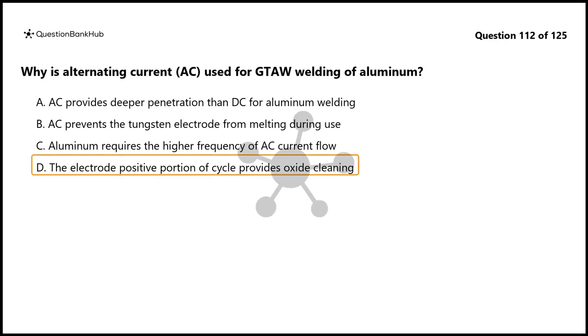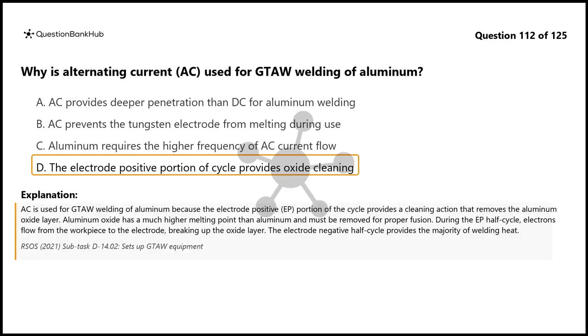The correct answer is D. The electrode positive portion of cycle provides oxide cleaning. AC is used for GTAW welding of aluminum because the electrode positive, EP, portion of the cycle provides a cleaning action that removes the aluminum oxide layer. Aluminum oxide has a much higher melting point than aluminum and must be removed for proper fusion. During the EP half cycle, electrons flow from the workpiece to the electrode, breaking up the oxide layer. The electrode negative half cycle provides the majority of welding heat.